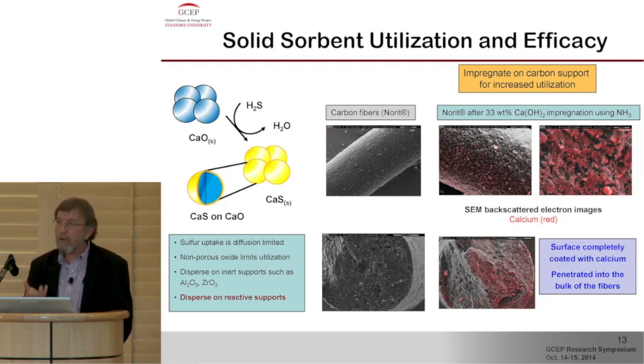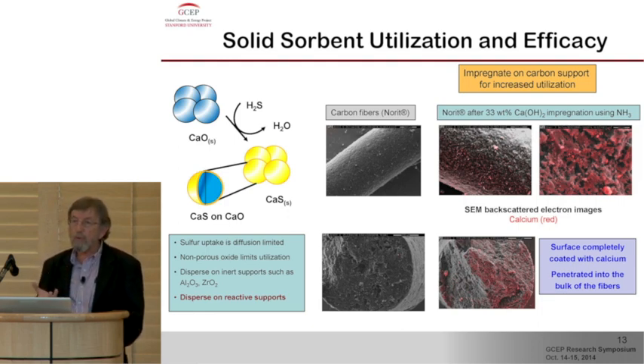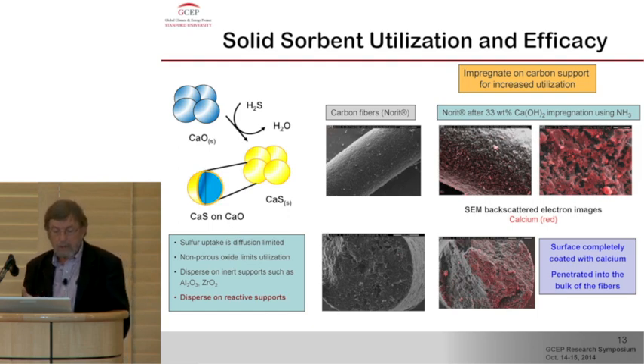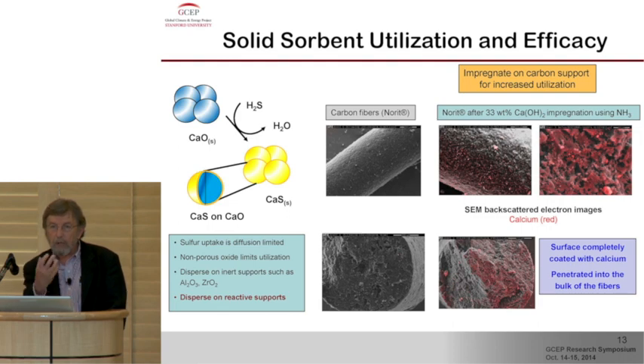What we would like to explore is something slightly different. We would like to try to disperse them on reactive or consumable supports, like carbon, for instance. In the same manner as the fuel in our fuel cell, we would like to load them onto carbon and get the sulfur to levels roughly below 10 ppm or so, that we think our oxide-based anode materials will be stable to. So this is the SEM picture of a carbon fiber. We chose these fibers so that we could identify and see where we are in terms of their loading. It's easier to work with them rather than with powdered carbon or coal.